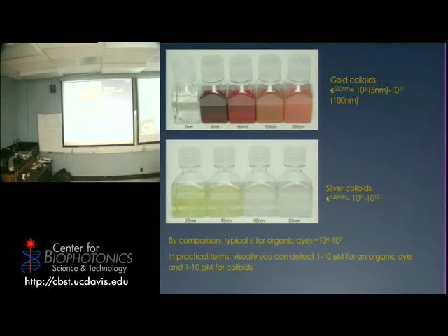These guys go to 10 to the 11. So what it means to you basically is that in terms of concentration, if 1 micromolar is visually pretty much at the limit where you can see a normal chromophore, these guys you can go down to like 1 picomolar, and actually you can go down even more than that. And you can start seeing why they are important, because if you can somehow couple them with something that you can detect analytically, you can see almost single molecules. And how would you see those?